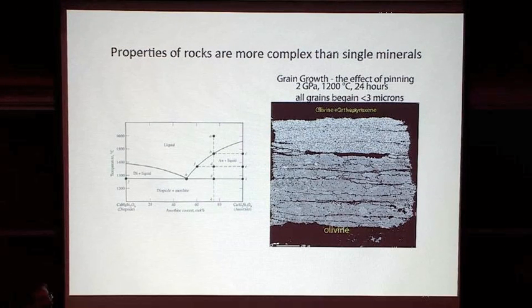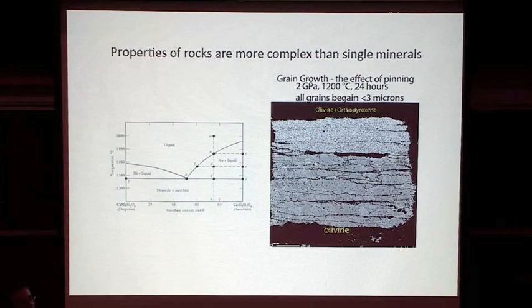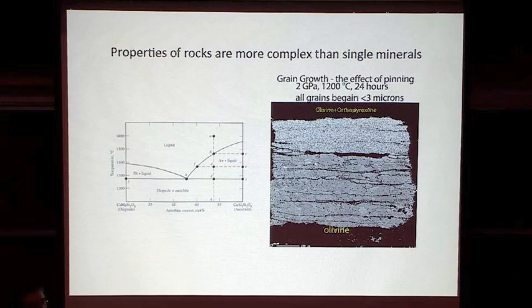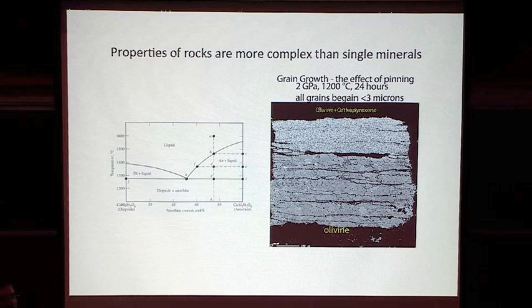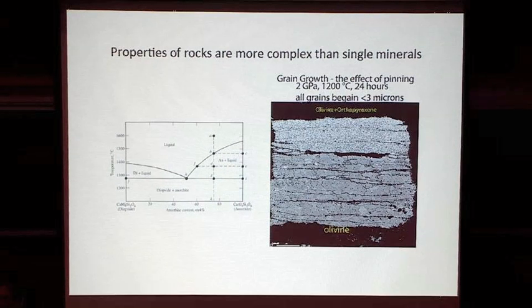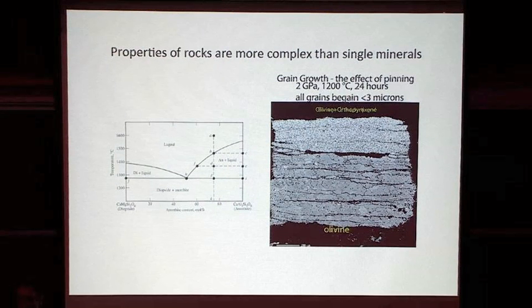I guess if the former lithosphere that's going down has remnant anisotropy, when you transform to perovskite and you sort of restamp that, you could lose the anisotropy, and you have wave path systematics that are actually affected by that and map into tomographic models. That could be there. But to argue against that, one might say, well, the tomography that shows the blues going through the 660, the blues don't suddenly disappear. Maybe not, but that might relate to just what Barbara said, it's still cold. But some blues, actually, most blues disappear.